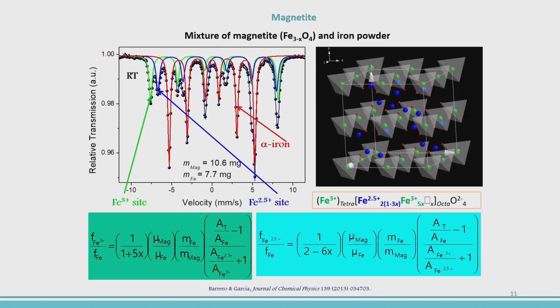Okay, so look, I'm going to show 3 examples of this method that we propose, the extension of the area. We are going to start first with the case of magnetite. This is a non-stoichiometric magnetite, here X equal not 0. So look, we are using this formula. We have to start with a guess of where the iron is located in the tetrahedral and the octahedral. So we propose this, but of course there is a controversy.